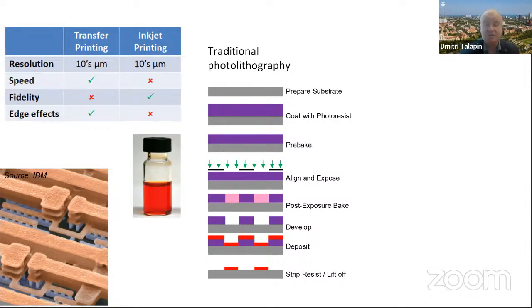On the other hand, in modern semiconductor technology, we heavily rely on lithography. Lithography uses photopolymers as photoresists. If you make a layer of photopolymer, you can expose it locally through a mask to UV light, and this exposure changes chemical properties, and you selectively dissolve exposed or unexposed regions. Then you can deposit and pattern materials. That works very well for vacuum deposition techniques. For solution deposition, like for quantum dots, it turned out to be not particularly efficient for two reasons. First of all, capillary forces redistribute material when you have a layer of photoresist with opened windows and then spin coat a layer of quantum dots or other solution processable materials. There will be huge capillary forces. And photopolymers often swell in solvents, and there are technical challenges.